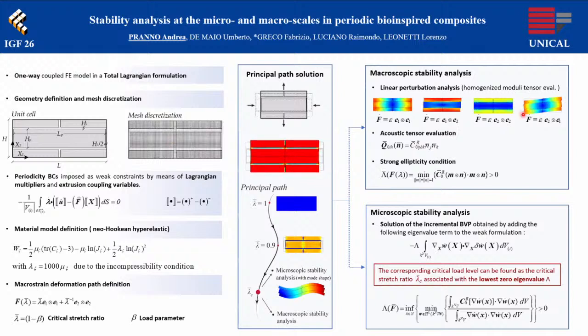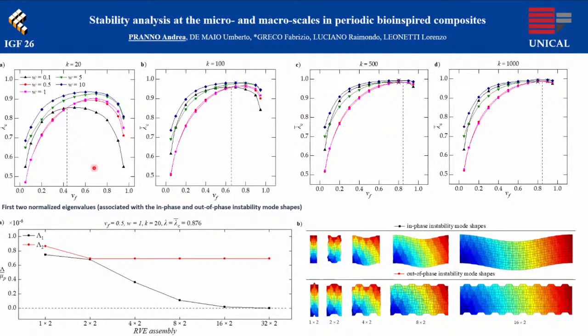The macroscopic stability analysis is performed in terms of loss of ellipticity condition by monitoring the minimum eigenvalue associated with the acoustic tensor, while the microscopic stability analysis is performed by monitoring the minimum eigenvalue associated with the microscopic stability functional. The results highlight that the critical stability mode shapes, together with their critical load factor and wavelength, are highly influenced by the geometrical arrangement and the material composition. From a general point of view, the critical stretch ratio has an increasing trend for low volume fractions until reaching a peak, and then a decreasing trend for high volume fractions.